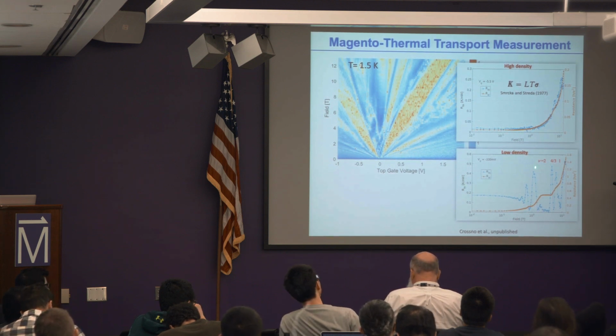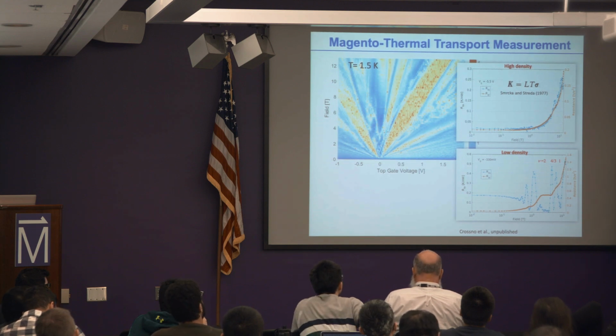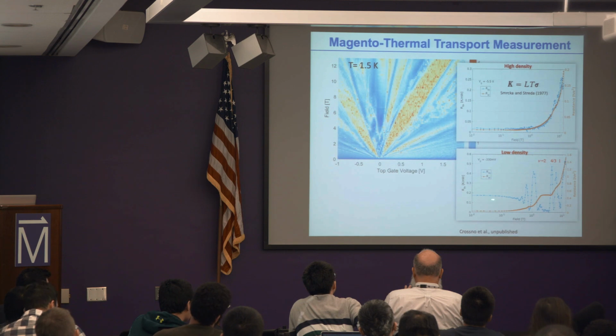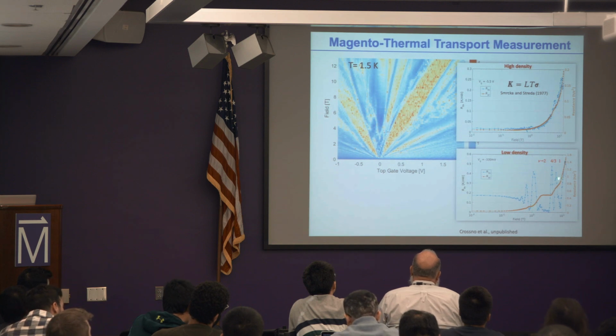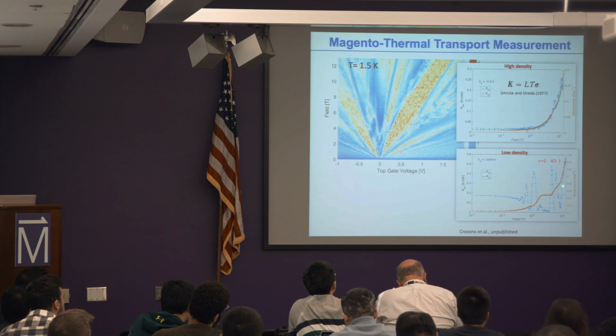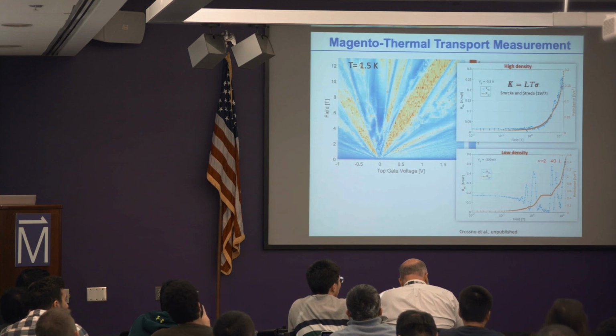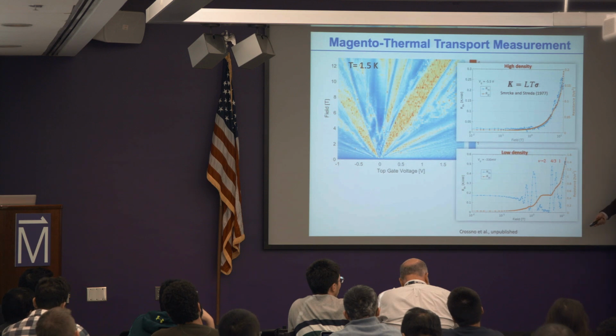But at the same time, we start to see nice oscillations appear in our thermal resistance data. It turns out thermal resistance is even more sensitive than electrical resistance. For example, in this particular sample, the fractions don't necessarily appear as nice plateaus, right? But in the thermal signal, we clearly see the fractions even appear in our thermal resistance signals, right? So in some sense, thermal resistance is more sensitive, and the Wiedemann-Franz law is apparently strongly violated here.